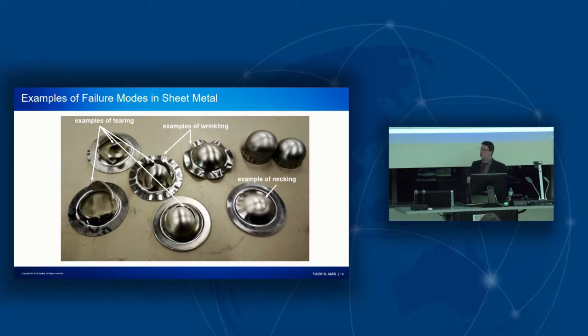Okay, so a quick word about some of the failure modes that we can see in sheet metal. I will note here, these parts are purposely failed because they're actually being used for materials testing. However, we can see a few examples there of tearing of the material, where the in-plane strain is simply too large to be supported by the sheet. We can see compressive strains, where we're warping the material out of plane, so that's wrinkling or buckling. And you can also see here an example of necking. Necking occurs prior to tearing, where you've got a thinning strain rate that's much higher than the strain rate of the in-plane material.